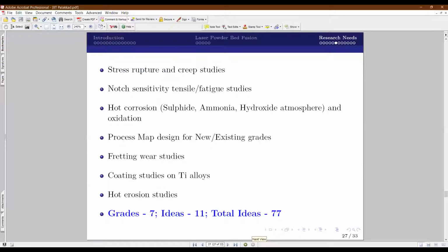And titanium alloys are prone to hot corrosion in a different ambience. So conventionally processed, like wrought grades, you have all the data for hot corrosion and oxidation, but for 3D printed, it's still evolving. Of course, like aluminum alloy, you can work on process map studies and fretting wear studies because your disc and blades are coupled by a loose fit, and those areas are prone to fretting, and in titanium alloys some of the regions are coated. So conventionally processed titanium components with a conventional coating may or may not work with the 3D printed one. So those areas need attention and to be explored.